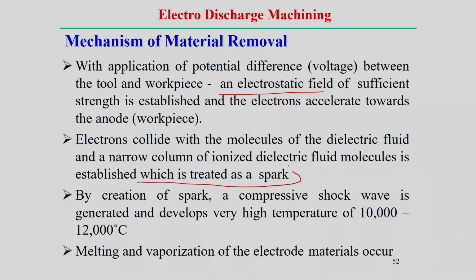That spark is basically responsible for the erosion of the material, and by the creation of the spark, a compressive shock wave is generated, and that develops a very high temperature, normally 10,000 to 12,000 degrees centigrade. That temperature is generated in this gap, and then finally melting or evaporation of the electrode material occurs, as well as the workpiece material. So, in that sense, the wear of the tool is a more serious problem in the electro discharge machining process, apart from the removal of the workpiece material.